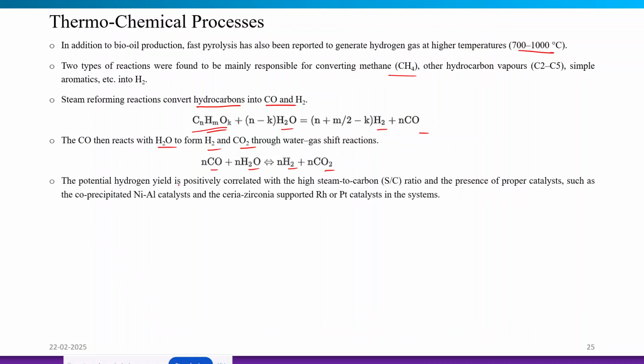The potential hydrogen yield is positively correlated with a high steam to carbon ratio in this process, and with the presence of a proper catalyst, such as a co-precipitated nickel aluminum catalyst, or other catalysts like ceria zirconia supported rhodium or platinum catalysts in the system. So these catalysts are important.